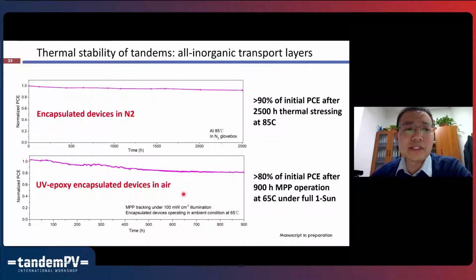Recently, we further studied the thermal stability of the all-perovskite tandem devices. We found that the organic-based charge transport layers are a big problem for thermal stability, especially the PEDOT layer in the narrow bandgap subcell. If we replace these organic charge transport layers with inorganic metal oxide-based charge transport layers, we can considerably increase the thermal stability of the devices. For example, we keep the devices in a glovebox with a simple encapsulation, and the devices can still maintain 90% of their initial efficiency after 2,500 hours of thermal stressing.